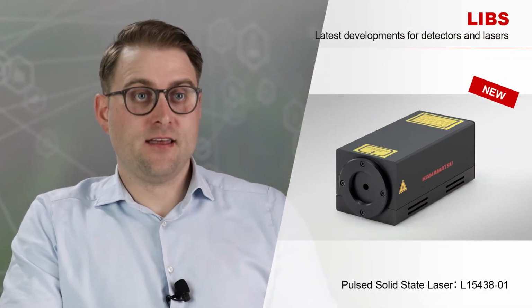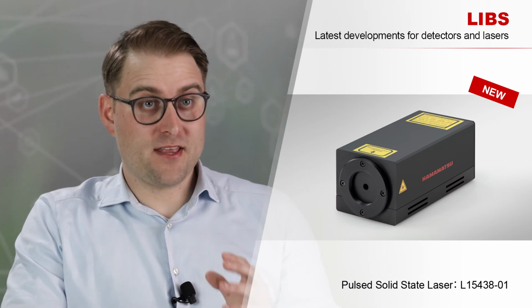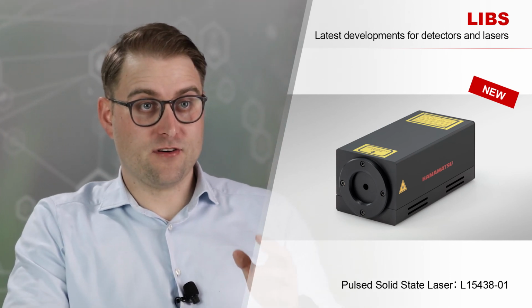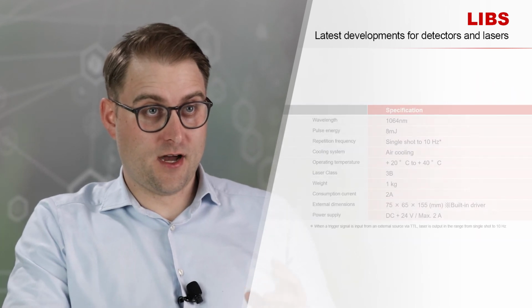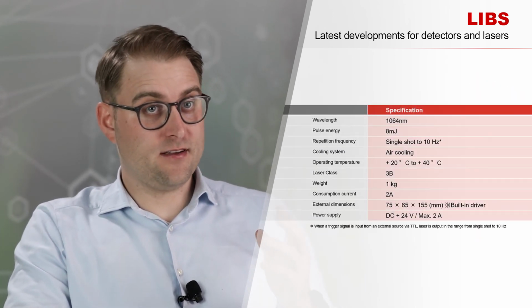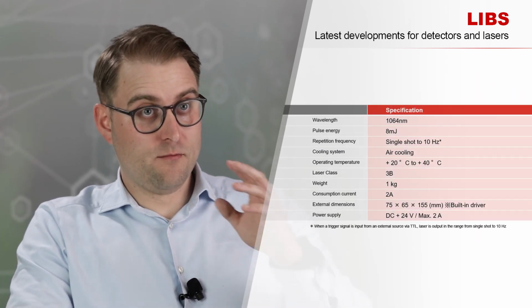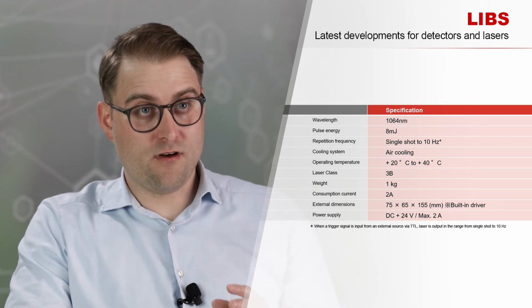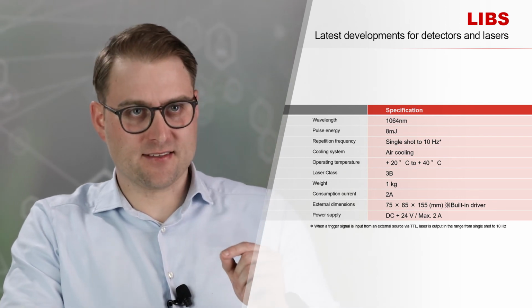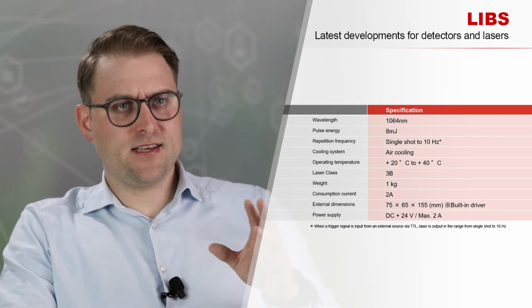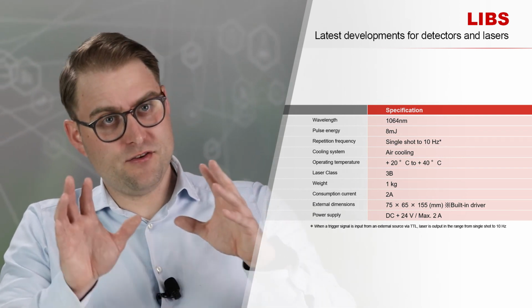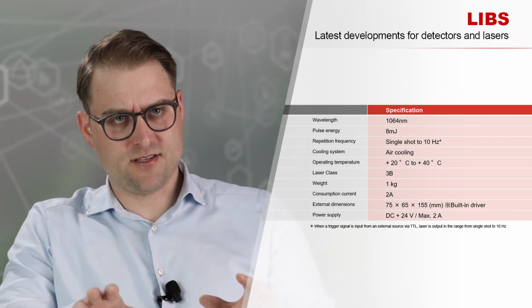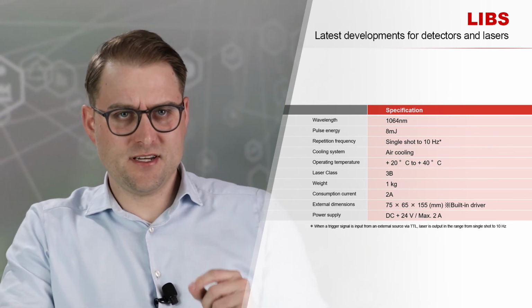In the previous slide, this laser was already marked with a red dot as a high power and short pulse version for LIBS. High power means up to 8 millijoule per shot with a pulse width of approximately only 2 nanoseconds. It is possible to apply a single shot, but you can also apply up to 10 Hz shots. To run this unit, you only need to connect a power supply and a trigger generator, which makes it very easy to use.